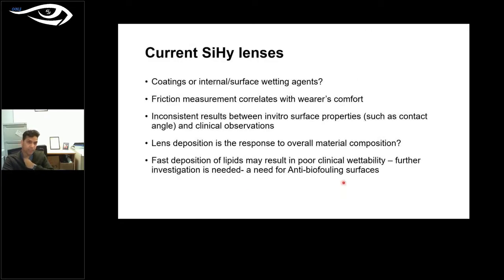What we understand from the current silicone hydrogel lenses is that coatings or internal surfacing agents. So should we have coatings, or should we promote internal surfacing agents? We have seen some mixed results from the studies that have been done. One thing definitely comes up, which is friction. Friction measurement is very important, because it strongly correlates with patients' or wearers' comfort. There have been some inconsistent results, particularly on whether in vitro surface properties actually match clinical observations in terms of breakup time and so on. So whether wetting angle or contact angle actually relates to clinical observations or not.